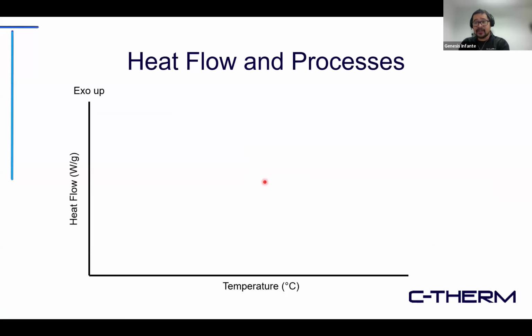The basic principle again for DSC is that typically we'll be looking at heat flow. As you can see here, usually in a normalized function, like in watts per gram, normalized against the mass of the sample. You'll see it typically on the y-axis as a function of temperature. This can also be easily interchanged as a function of time, where the rate of temperature change is also added in the graph. Another important thing that we would be looking at in DSC graphs is a directionality indicating which direction is exothermic and which direction is endothermic.